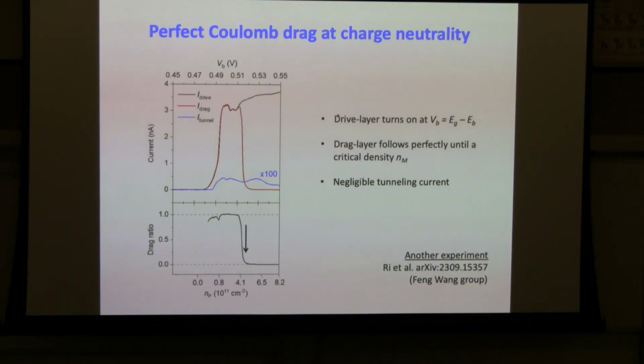And then remind me why they move. Okay. There's a chemical potential that's different. So there's a chemical potential for the excitons that's different at one end than the other? Yes. If it's a superfluid phase, then the chemical potential difference will only drop at the contact, right? And that's the driving force for the electron current in the electron layer. And the hole layer current just spontaneously responds to the drag. Yes, so perfect Coulomb drag over this range, and then zero drag immediately outside this range.